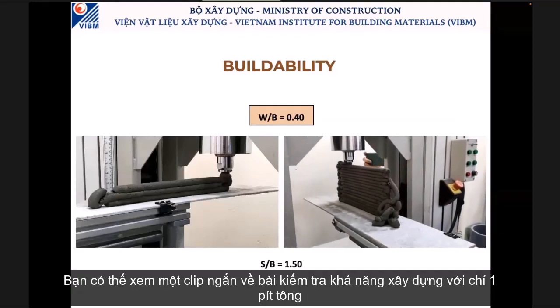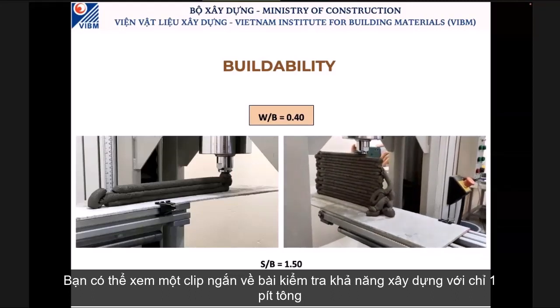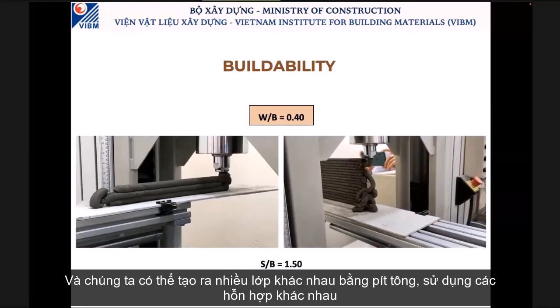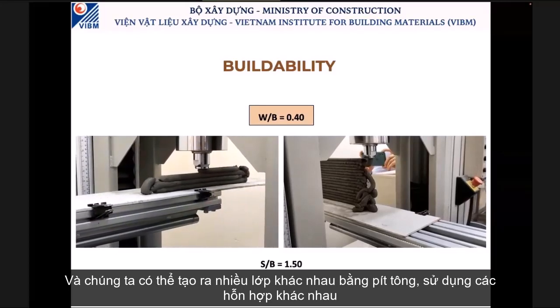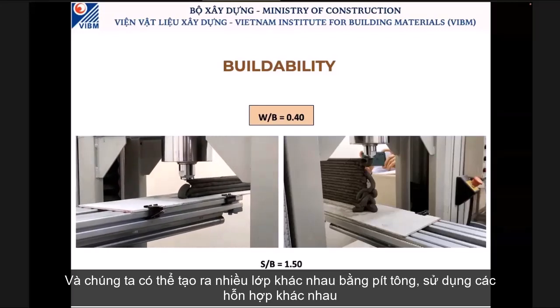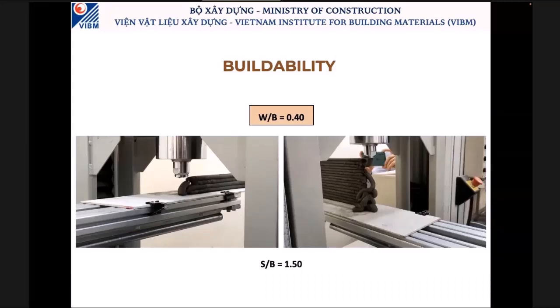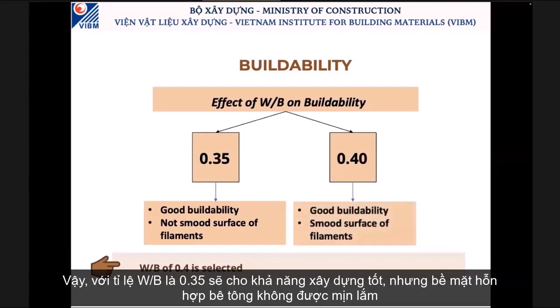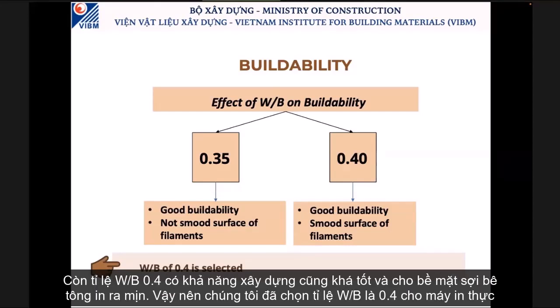You can see a very short clip to show we test our ability with only one single layer, one single bit, and it can build with different layers, using different mixes. So the buildability with water binder ratio 0.35 mix also has good buildability, but it's not really a smooth surface of filament. With 0.40, quite good buildability, and smooth surface of filament. So we select water binder ratio 0.4 for tests in the real printers.